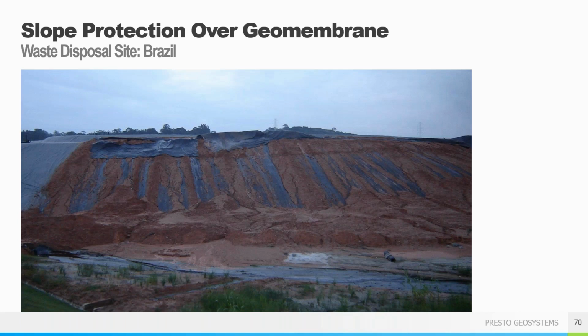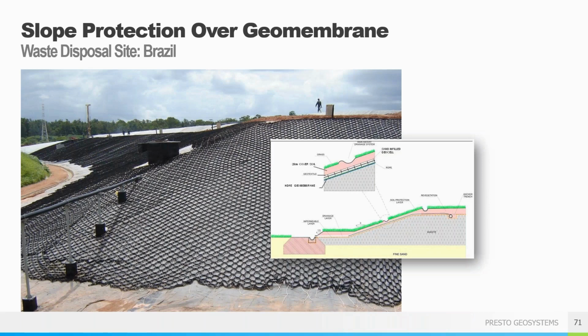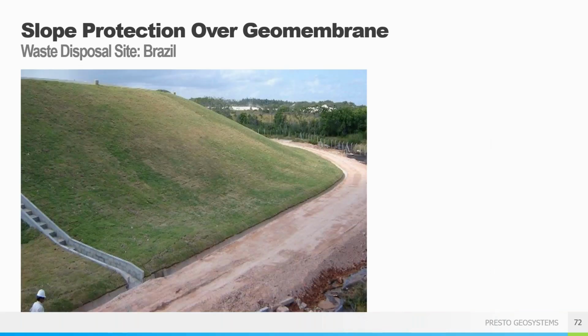Here's another project, this one at a waste disposal site in Brazil. You can see we have significant erosion after the failure of the initial two-dimensional cover system that was selected. Here's the permanent solution, which consisted of a geomembrane covered by the GEOWEB, anchored using the tendon system. Many times the deadman pipe can be placed in the same anchor trench as the liner for ease of construction. One year after the installation, we've got a fully vegetated, erosion-resistant cap in place.